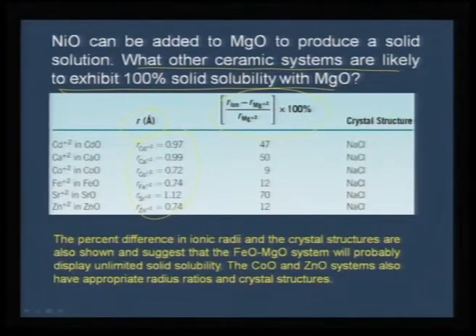So, based on this particular composition or this formula, where you can substitute this value and calculate the percentage ionic capability or compatibility, then you would arrive at some numbers. These are the numbers which will tell you whether substitution of such metals are possible. For example, you would see the error involved is only 9% for cobalt substituted in magnesium oxide, or 12% for iron 2 plus substitution in magnesium oxide. Therefore, in this whole list, you can actually single out that these two can actually go into the lattice comfortably.